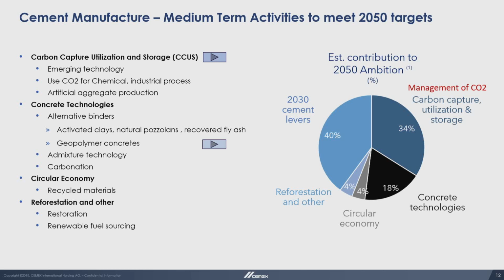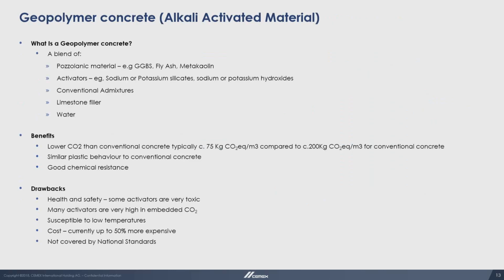There are many power stations around the UK where there are lagoons of fly ash, and work has been done in the past by a number of companies to recover that fly ash to reuse it in concrete. Historically, the issue has been really around the cost, and it not being cost effective. However, as we see the cost of these secondary cementitious materials increasing, maybe their time has come and there will be an economic incentive to reuse these materials. Geopolymer concretes or alkali activated materials are also another area, and I noticed in a couple of the earlier presentations they were referred to. Geopolymer concretes, what is it? Well, they're effectively concretes manufactured without any cement clinker in them.